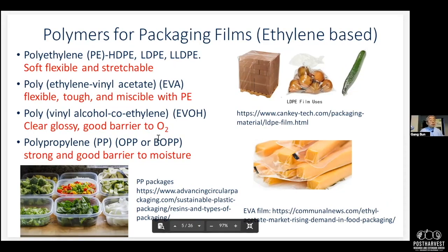Polypropylene. We all know polypropylene. We use a lot of polypropylene. And mostly you see the boxes and the containers made of polypropylene. But polypropylene can also be made into films. A little bit stronger, it's a good barrier to moisture. And in fact, all the polyethylene, all what we call the olefin polymers, are good barriers to moisture because they are super hydrophobic.